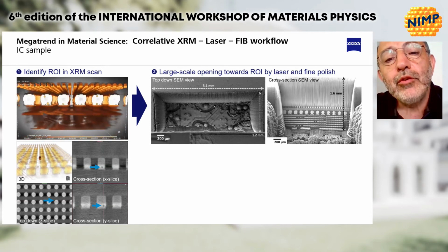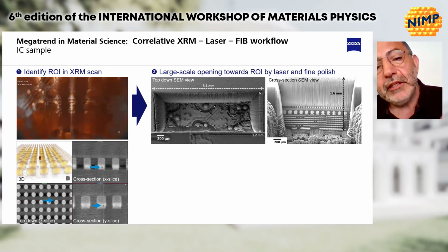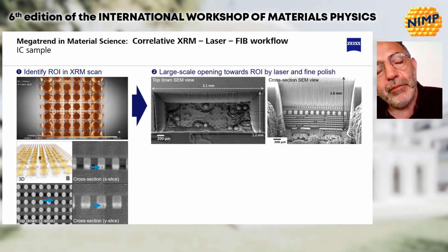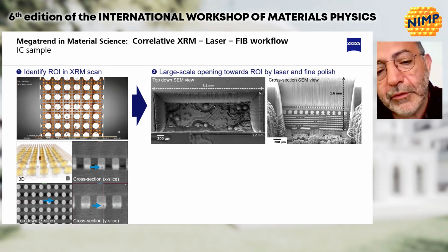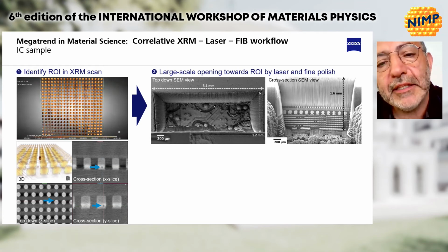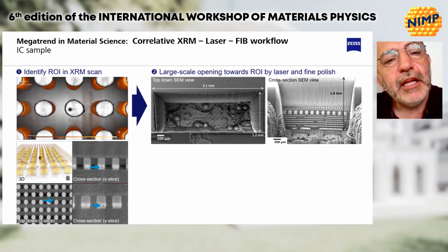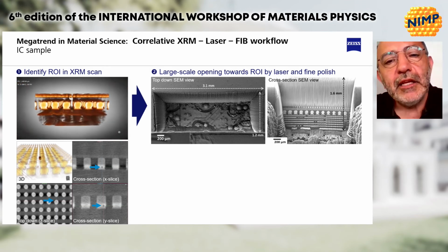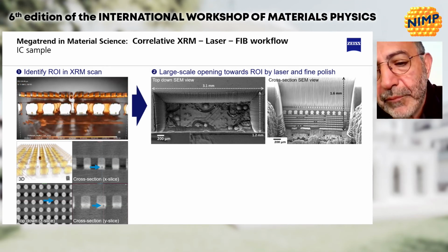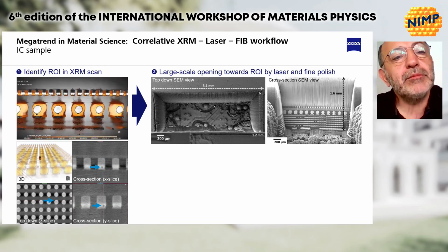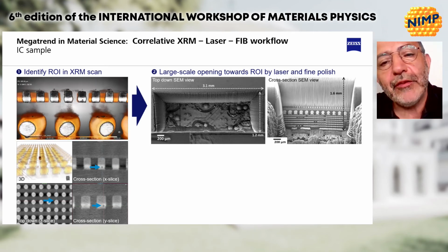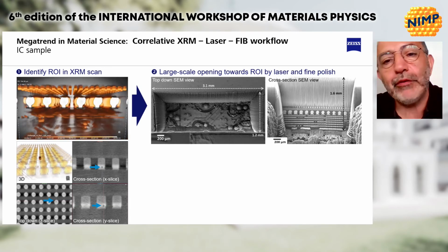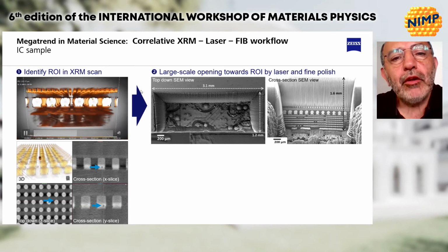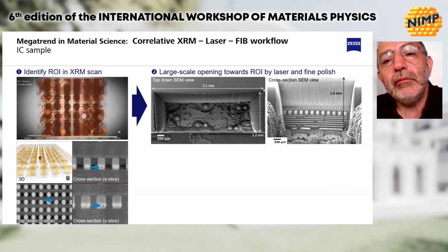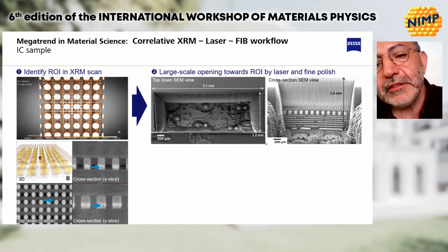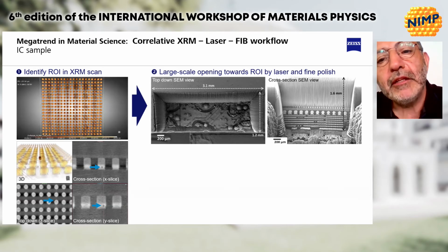And then you need to just cut. You can imagine a microchip. This is a relatively big sample of at least 6 by 6 millimeters in size, and a thickness of a few millimeters, and you want to go really very deep inside. If you try to do that with a dual beam or a FIB system, it is more or less impossible, because you will need days just to reach the area of interest. In this case, we use a correlated tool, which includes a laser, a femto laser, just to cut very deep into the samples at the regions of interest.